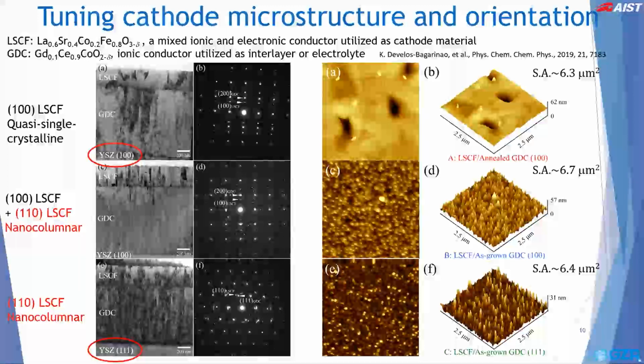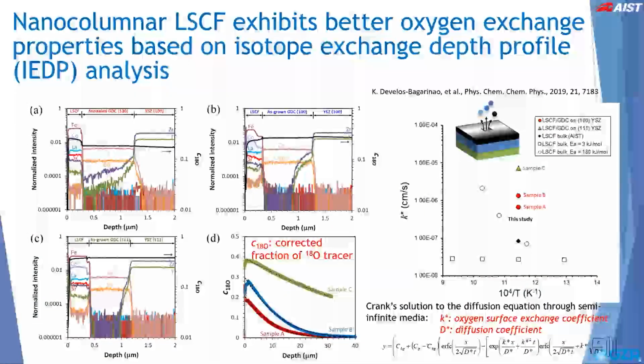These are transmission electron microscopy or TEM images showing the cross-sectional microstructures of the different films, together with the selected area electron diffraction patterns and atomic force microscopy images obtained for each film. In particular, we were able to obtain three different types of LSCF, ranging from quasi-single crystalline with a dominant 100 orientation, mixed orientation of 100 and 110, and to a dominant 110 LSCF orientation. The main question is, how do the films behave in terms of oxygen surface exchange properties?